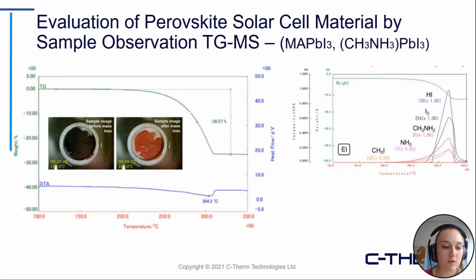Okay, so I wanted to bring this quick application highlight on screen just so you could see that Rigaku's instruments do have some evolved gas analysis capabilities as well. With this example, we are looking at a solar cell measured with TGMS. The powder was heated at 10 degrees C per minute from room temperature to 350 Celsius in a helium atmosphere.